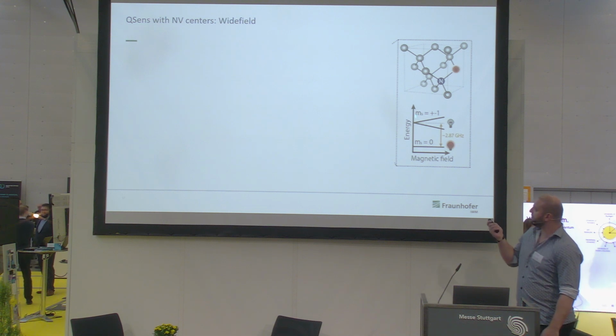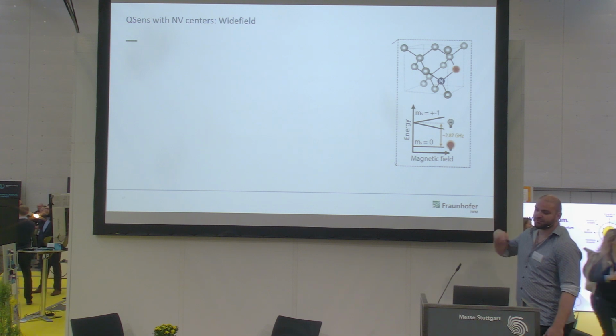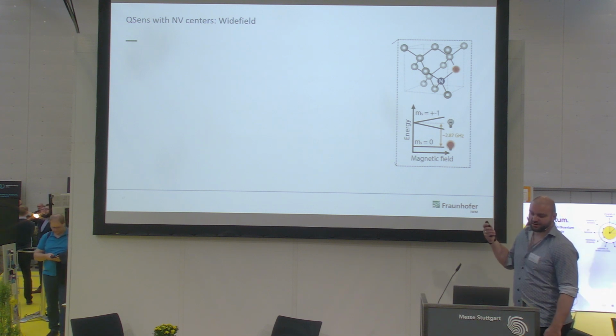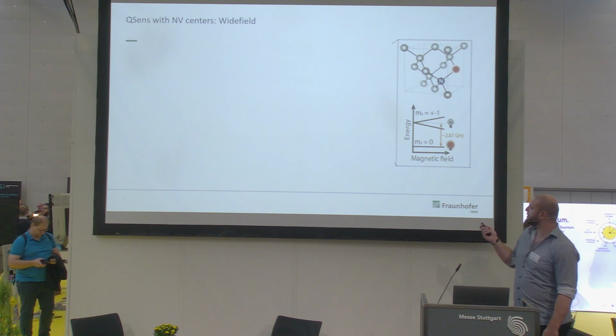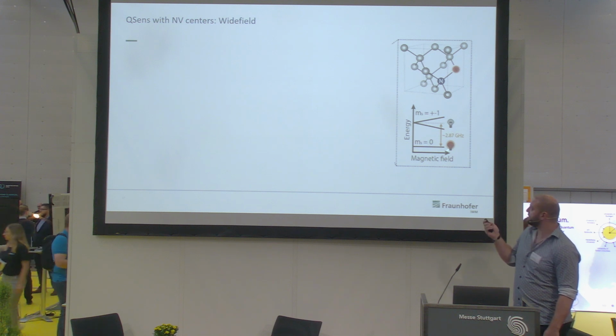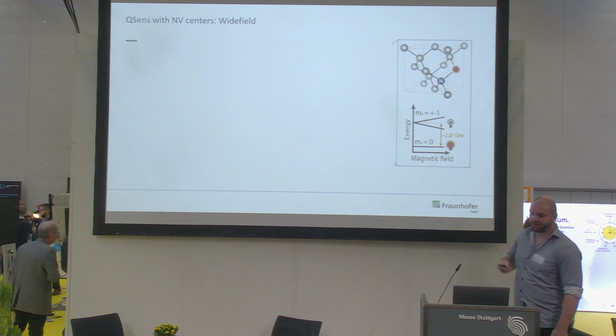And the NV ground state here is sensitive to magnetic fields via the Zeeman splitting, and we can read it out with a green laser. And if we do this from the zero state, it shines very bright. If we do it from one of the plus-minus states, it's very dark.